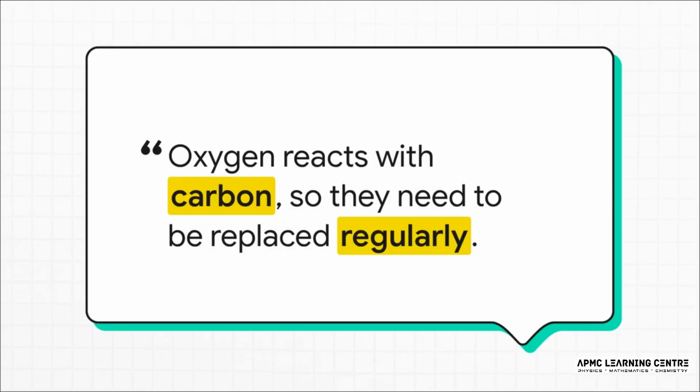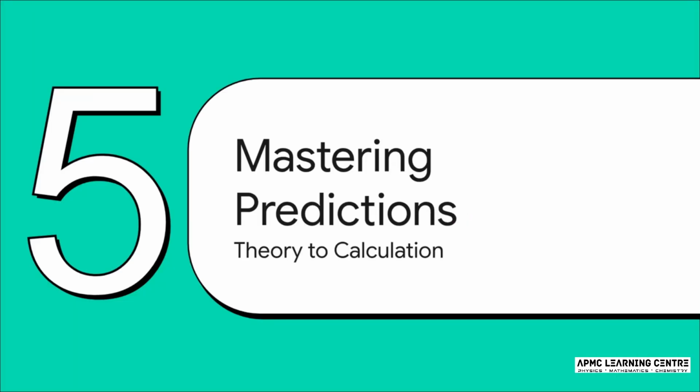And hey, here's a neat little practical tip for you. That oxygen you produce in dilute solutions is pretty reactive. If you're using carbon or graphite electrodes, that oxygen will actually start reacting with the carbon, essentially burning your electrode away into carbon dioxide. So over time, you'd have to keep replacing it. Kinda cool, right?